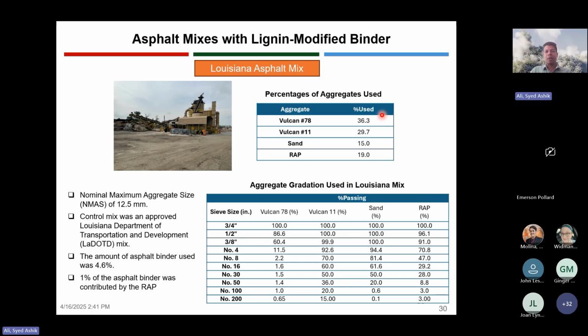The aggregates that were used in this asphalt mix, you can see here. I want to draw your attention to the RAP portion of it. This mix already had 19% RAP, and it obviously had some impact on the mix performance as well. The amount of asphalt binder used to produce these asphalt mixes was 4.6%. Around 1% of the asphalt binder was expected to come from RAP. And here is the aggregate gradation that was used by LSU to produce this asphalt mix.